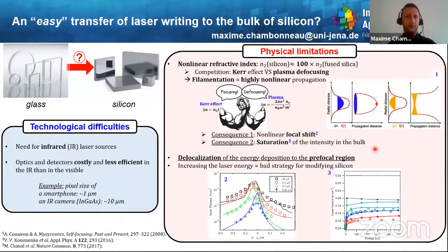So the question now is: is it easy to transfer the whole knowledge about laser dielectric interaction to silicon and basically do the same? Well, sadly, the answer is no. And there are two main reasons for that. First, there are some technological difficulties, especially if you want to functionalize in volume silicon wafers. As you can see here, silicon is not transparent to visible light, so you will need infrared ultrafast laser sources. Moreover, you will probably need some optics and detectors, which are more costly and also less efficient in the IR compared to the visible.